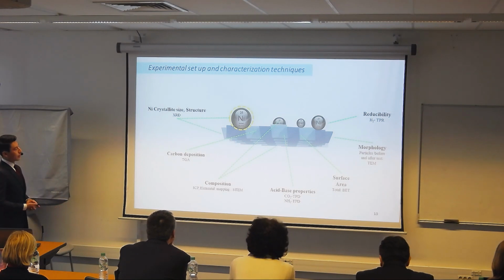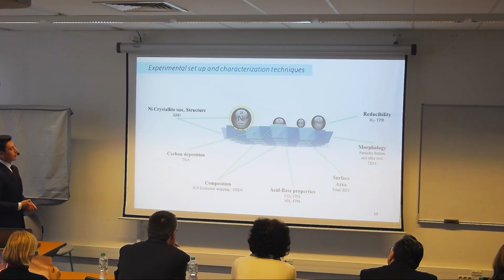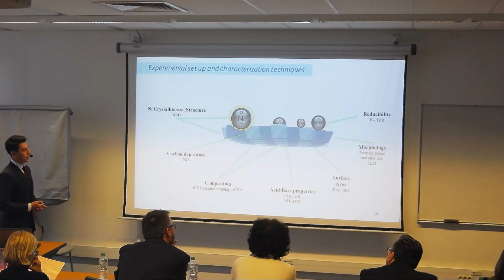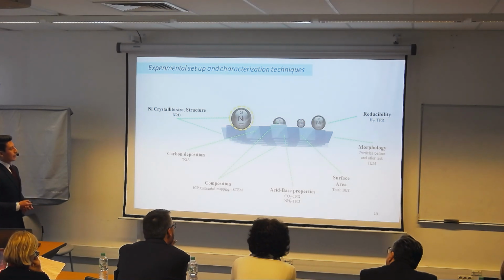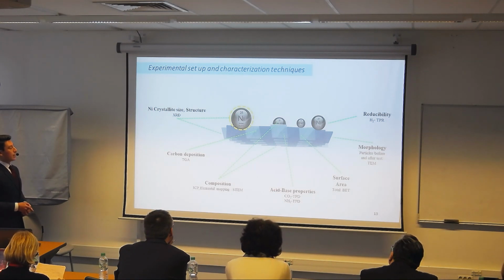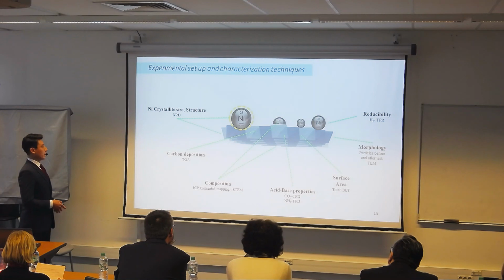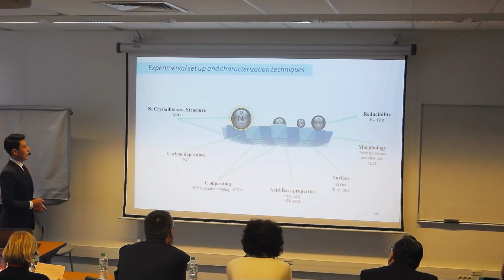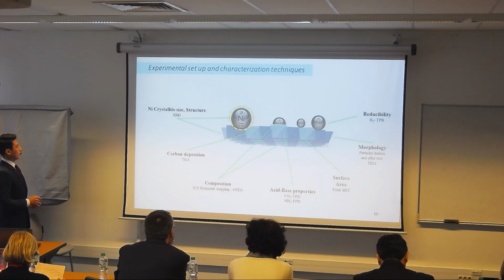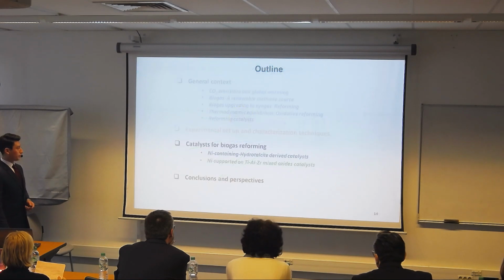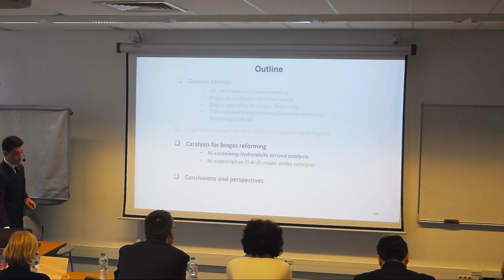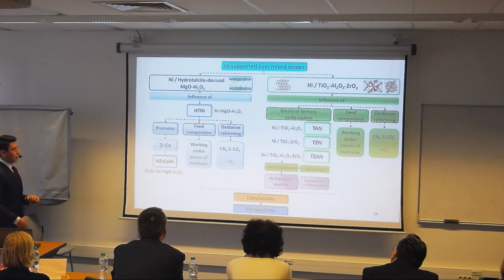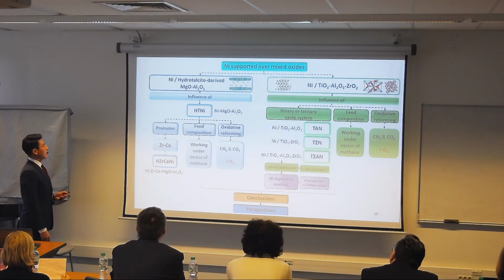Before and after the reaction, we are always interested in what's happening with our catalyst. So we used different techniques in order to know its properties, such as reducibility, morphology, surface area, and the basic properties present after the synthesis, as well as the composition. After the test we looked for the carbon deposition, and also an important factor, the nickel crystal size and the structure. So knowing this, I'm going to present to you now the catalysts that I've been using in order to reform the biogas.